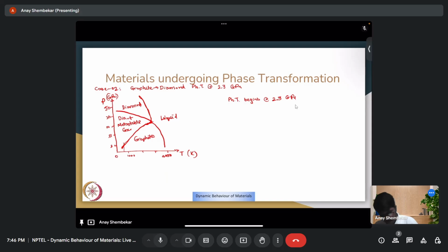Right. And what this results in is very small diamonds formed. What these diamonds are is they're typically martensitic phase transformation due to shock wave. It's martensitic, meaning the diamond formed is a hexagonal, HCP rather than cubic.